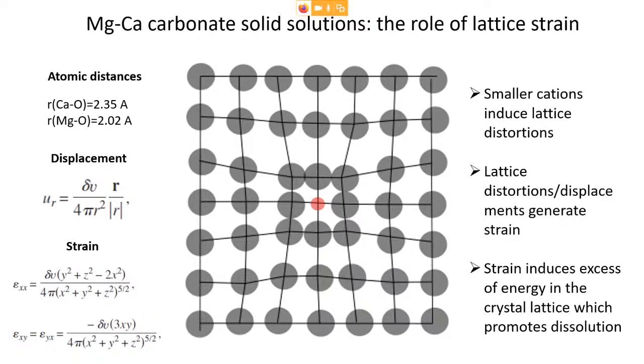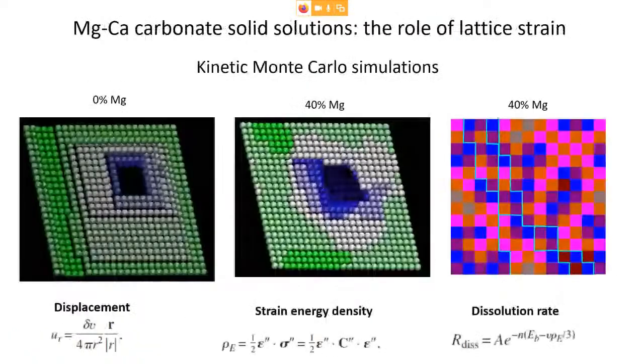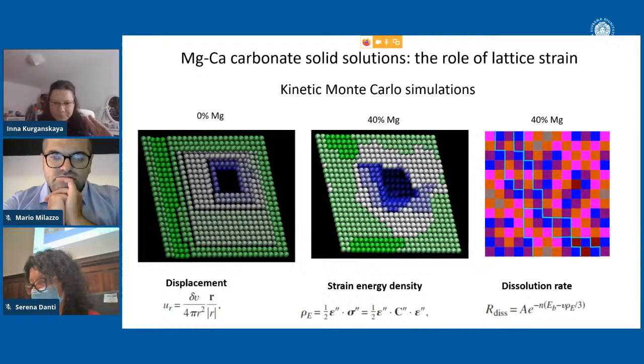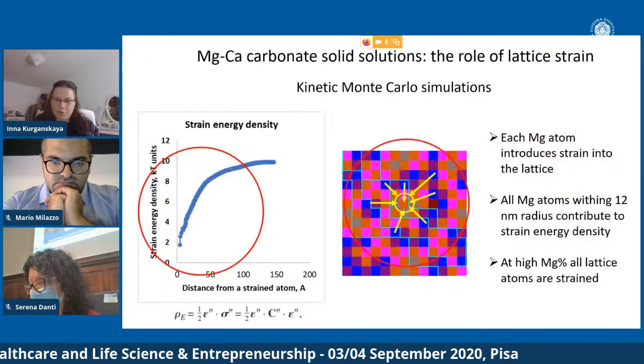Pretty much, the mismatch between the cation sizes causes displacement within the lattice, and the displacement causes strain. So the lattice is internally strained, and this strain induces excess energy, which means that the bonds are in general breaking faster than in the pure phases. So if we introduce lots of substituting cations into the material, the entire lattice becomes strained. And in general, strain energy density can be calculated. I did it for calcium carbonate, and it can be calculated by using strain tensors and other computational approaches, and all this information for the strain energy density comes into the equation for the dissolution rate. In this way, we can understand the role of the strain.